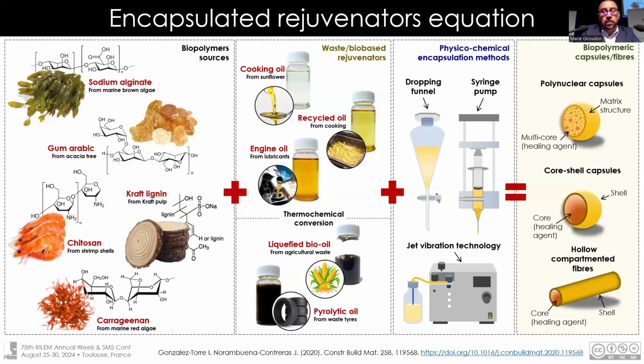In my vision, the following equation can define the preparation of the encapsulated rejuvenator for more sustainable roads. Basically, you can use a biopolymer source to replace the polymer based on petroleum. You can use sodium alginate, gum arabic, kraft lignin, chitosan, and carrageenan, plus several rejuvenators, alternatives to the conventional rejuvenator materials. You can use cooking oil, recycled oil from McDonald's or Burger King, engine oil, and at the same time, you can produce specific rejuvenators by using thermochemical conversions, including pyrolysis and hydrothermal liquefaction, to produce, for example, liquefied bio-oil or pyrolytic oil from end-of-life tires.